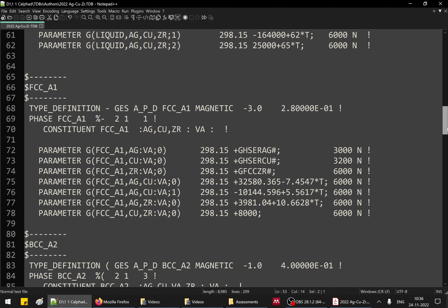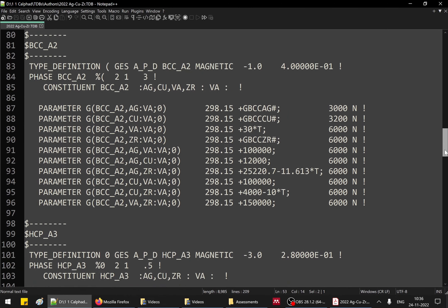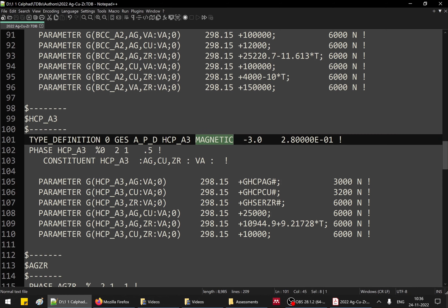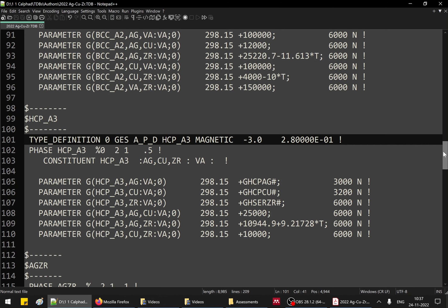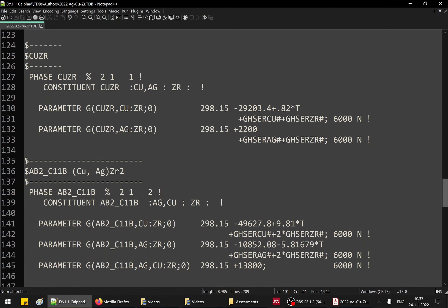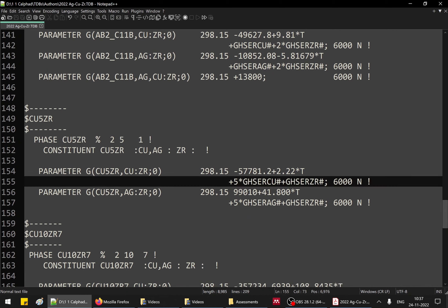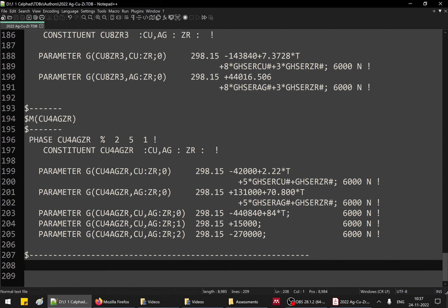Like this, every phase is described — FCC, BCC, and so on. Some extra contributions can be appended: for example, in the GES module using the 'append phase description' (APD) command, a magnetic contribution is appended for the HCP phase, and ordering contributions can be appended similarly. Once everything is compiled, reference numbers like REF followed by a number can be added before the exclamation mark, and all references can be described at the very end of the file. That covers the TDB file structure.